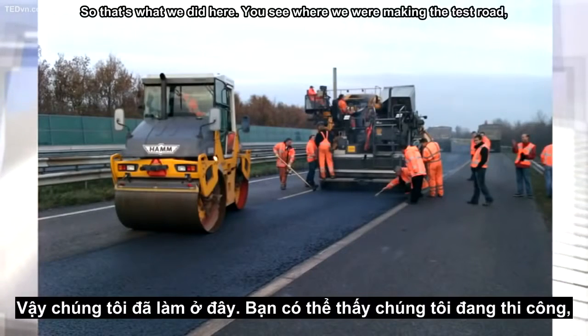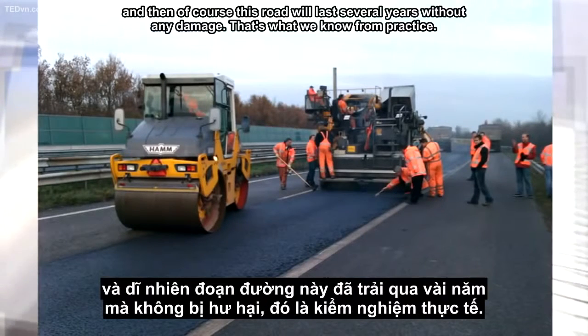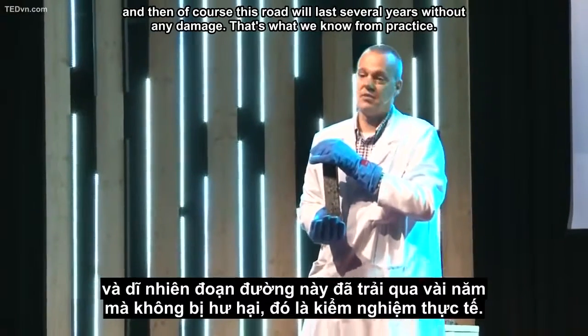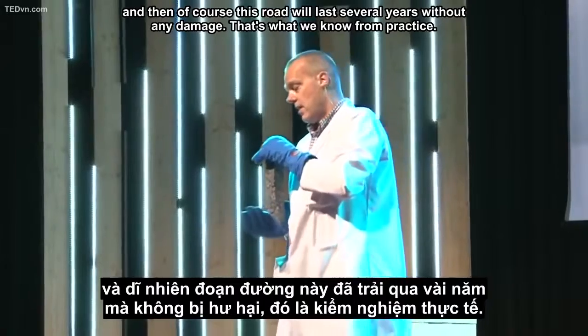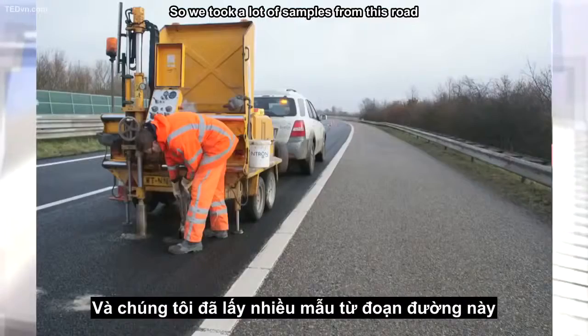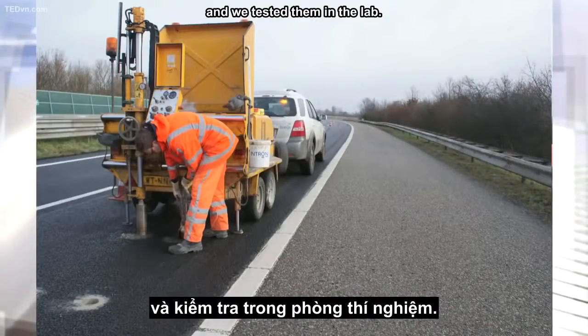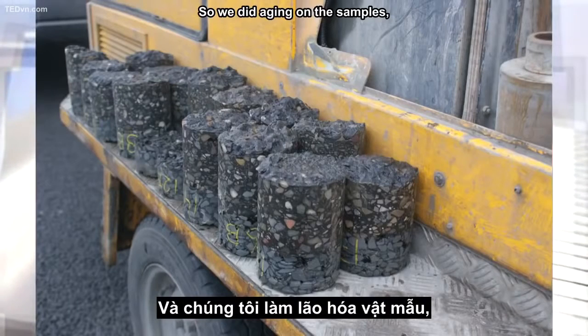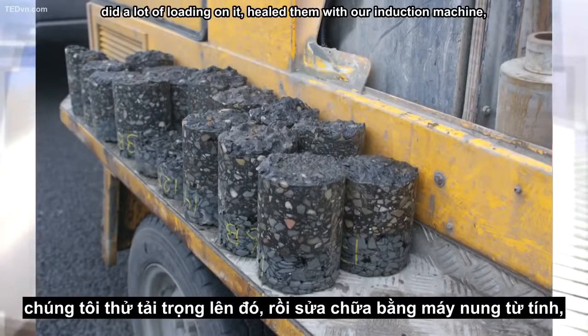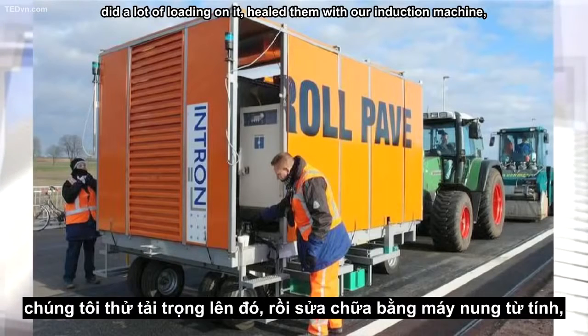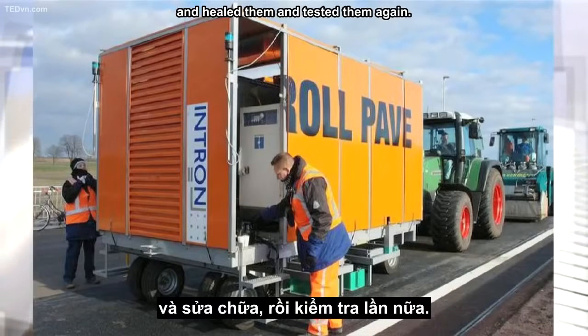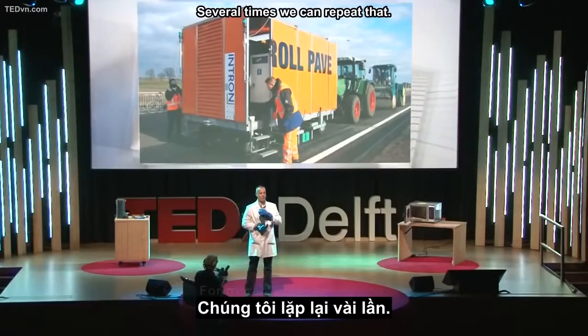So that's what we did here. You see where we're making the test road. And then, of course, this road will last several years without any damage. That's what we know from practice. So we took a lot of samples from this road, and we tested them in the lab. We did aging on the samples, did a lot of loading on them, healed them with our induction machine, and tested them again. Several times we can repeat that.